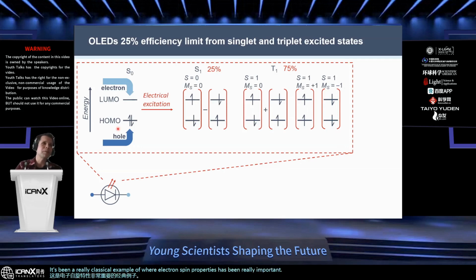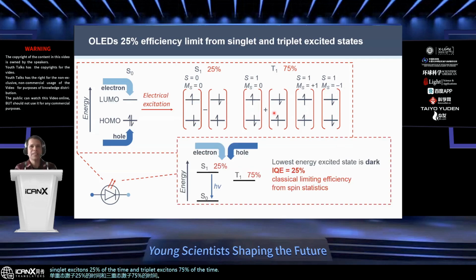If you take a material which has a classical electron configuration like this, where electrons are filled up to the HOMO and unfilled from the LUMO, with a singlet ground state, on electrical excitation you form singlet excitons 25% of the time and triplet excitons 75% of the time. And as I set out in my abstract, what I wanted to put across was that in molecules, the spin of your ground state and your excited state really dictates what photophysics can happen.